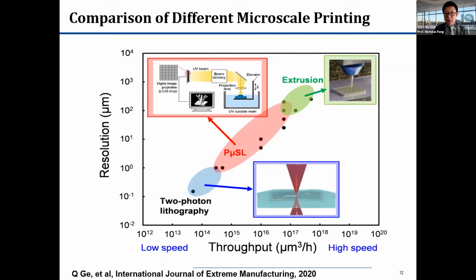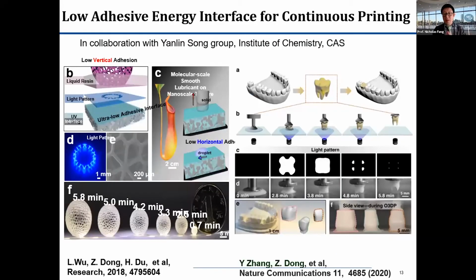And currently, we are able to already generate something that is on the scale of 25 centimeters or so, and yet maintaining a feature size of micrometers or smaller. So how did we do that? We find that there are a couple of challenging issues that limit the scalability of this photonic-based process. One of them is associated with, so to speak, the adhesion and friction that are required to move the fluid. The thinner the fluid layer, the higher the, so to speak, viscosity or pressure drop that we have to combat with.